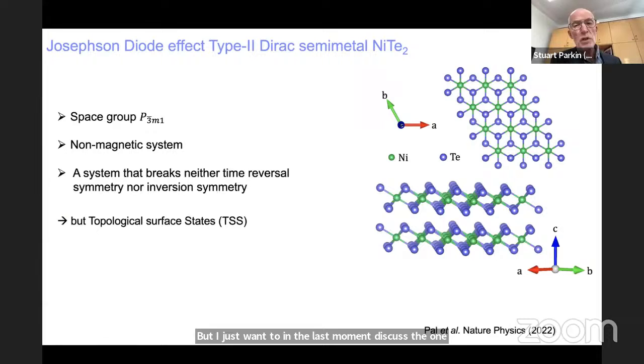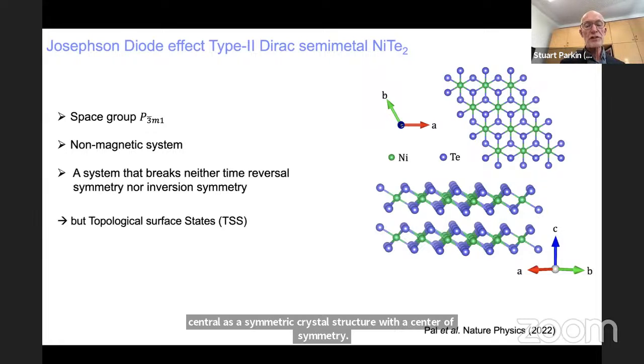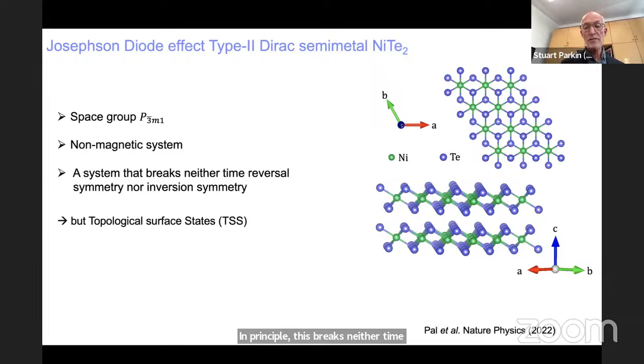This is the first work on a 2D Van der Waals non-magnetic system, nickel ditelluride. So it's non-magnetic and has a symmetric crystal structure with a center of symmetry. In principle, this breaks neither time reversal nor inversion symmetry. However, it's a very special material with a Dirac semi-metal, and it has spin-polarized topological surface states. This is the reason why Banabir Pal, postdoc in my group, explored this system.